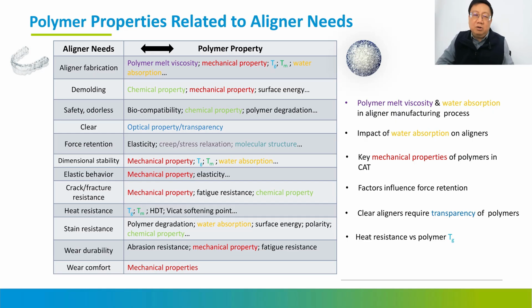I would say that for most of the polymer materials, not many people look at that, because patients want to wear aligners to drink hot tea or hot coffee, where the temperature is about 55 to 60 degrees C. And with some materials like PETG, the Tg is only about 70 degrees C, which means if you drink hot tea, the force will actually decay very fast. If you drink hot tea, there's almost a big influence on the orthodontic force. Then it will make the movable teeth lose their efficiency very quickly.